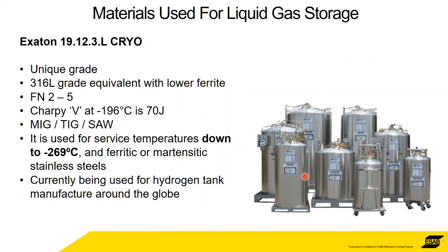So two grades that we have that I particularly want to mention because they're quite special. So we have a 19 12 3L cryo. So it's a 316L, but it has a much lower ferrite than a typical 316L. The ferrite is normally between 2 and 5, but normally it's 3. So with a ferrite number of 3, this means that it's usable down to minus 269. The Charpy value, the impact toughness at minus 196 is 70 joules. So this is certainly one of the materials of choice for hydrogen tanks.